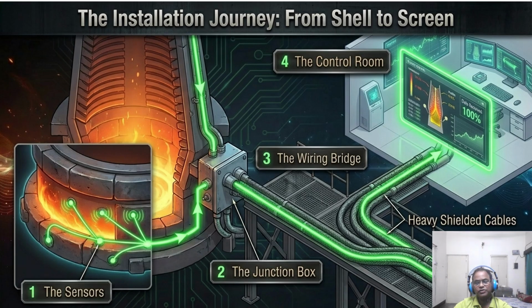So for a furnace of this capacity, we cannot rely on just one sensor. We install multiple sensor arrays around the entire circumference to detect if liquids are pooling unevenly, perhaps due to a blocked deadman. This is also a good way to measure the deadman configuration in the furnace. Whether this deadman is exactly in the center or symmetrical, we can find out from the electrical signals.